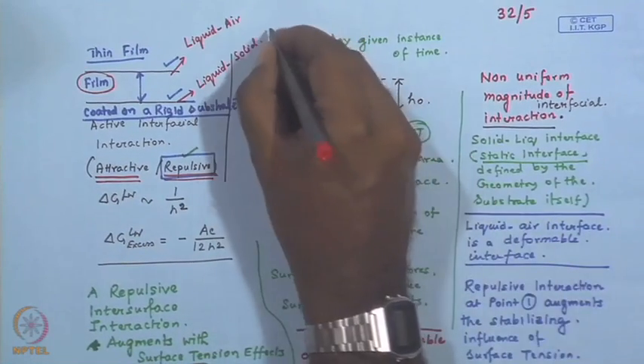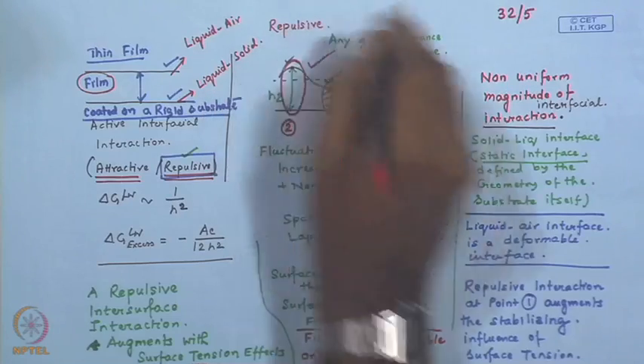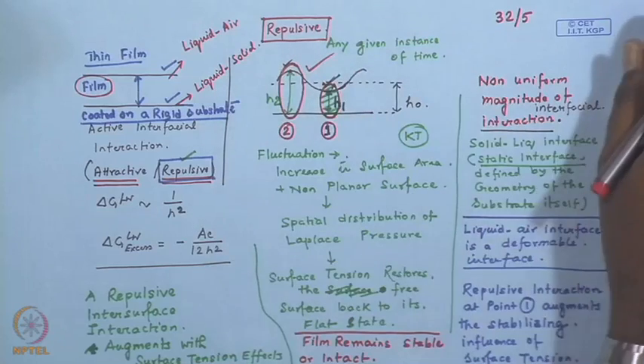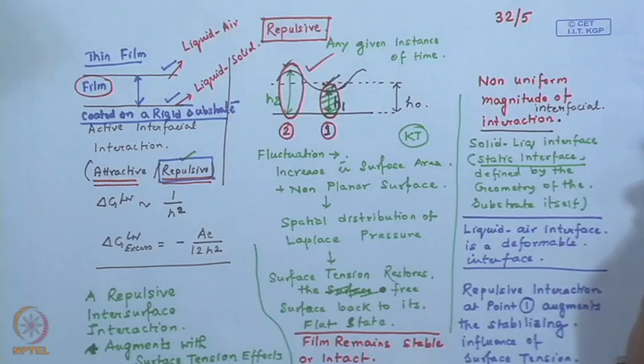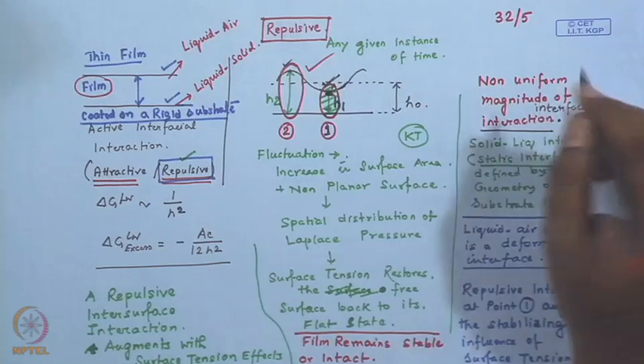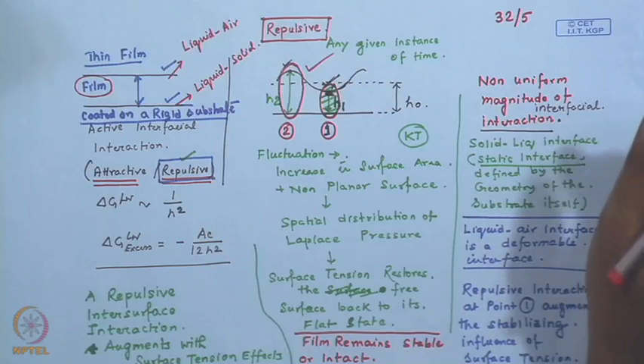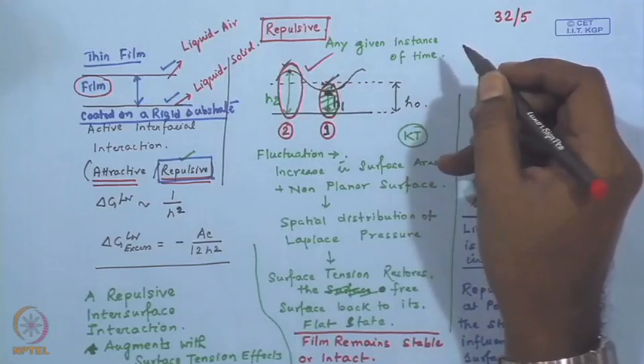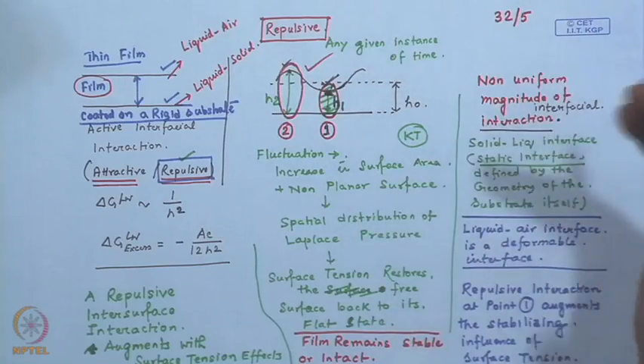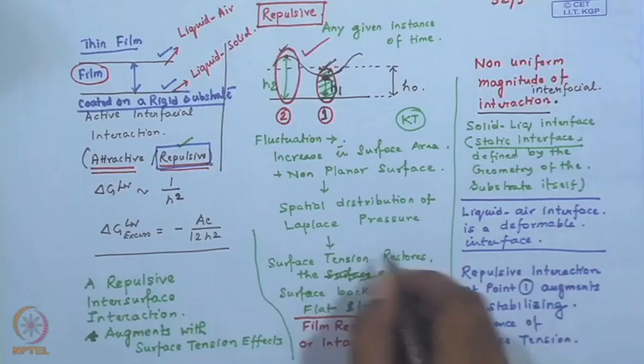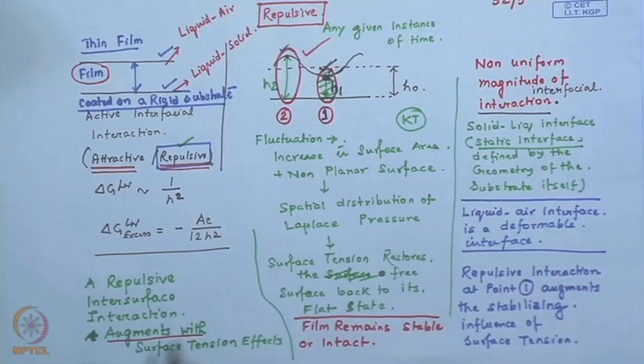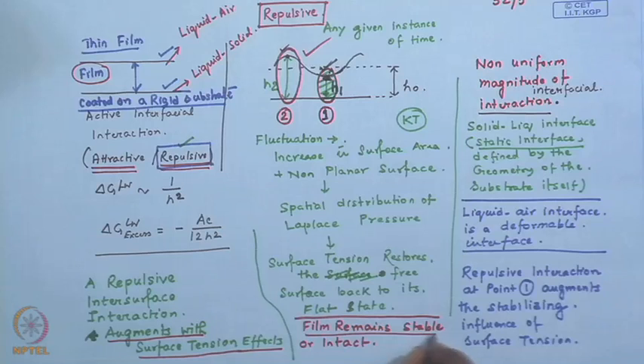There is an active interaction between these two interfaces, and this interaction can be either attractive or repulsive. We considered individually the two cases of attractive and repulsive interaction. In a situation where you have a repulsive interaction, the valley of any instantaneous surface fluctuation is a location where the two interfaces are closer to each other. Since there is an active interaction between the two, over here the repulsion is stronger as compared to the repulsion in this particular zone. Therefore, the repulsive interaction augments the stabilizing influence of surface tension, and the film remains unconditionally stable or intact.